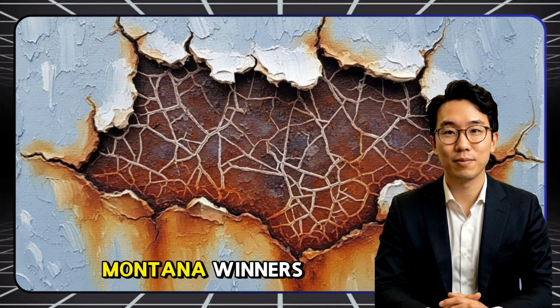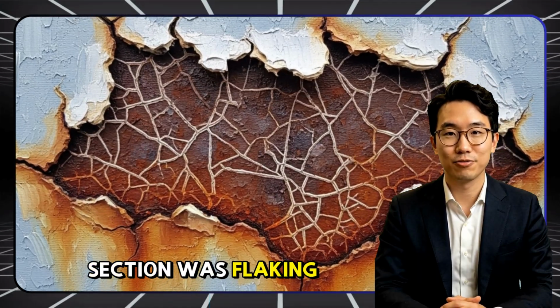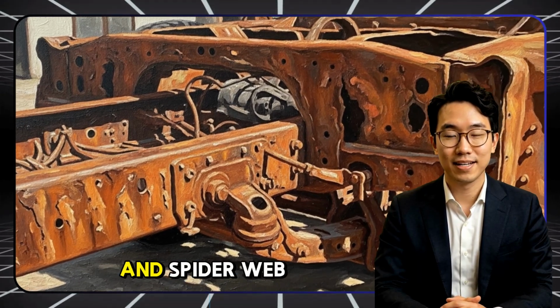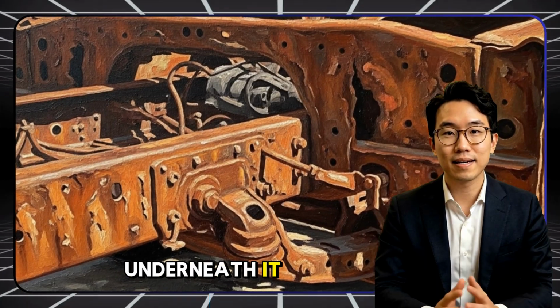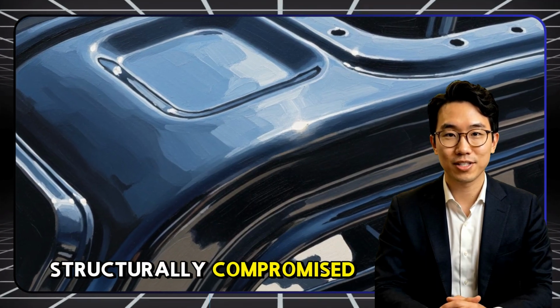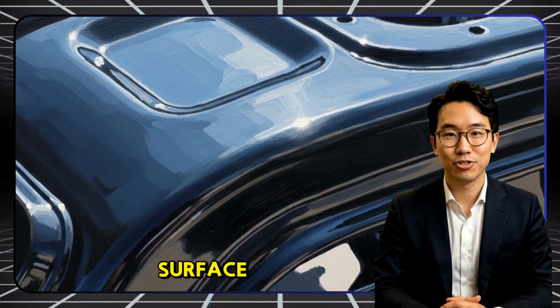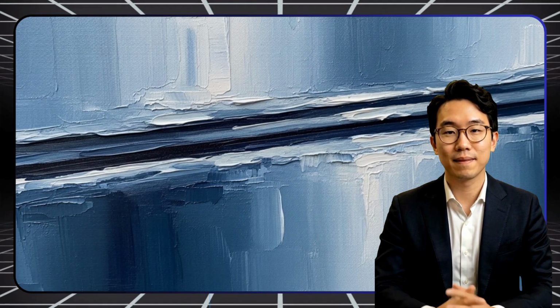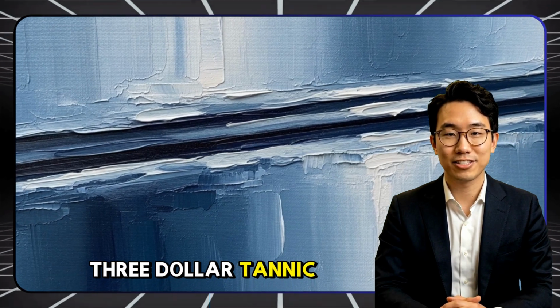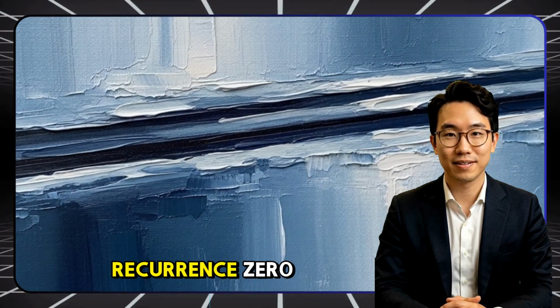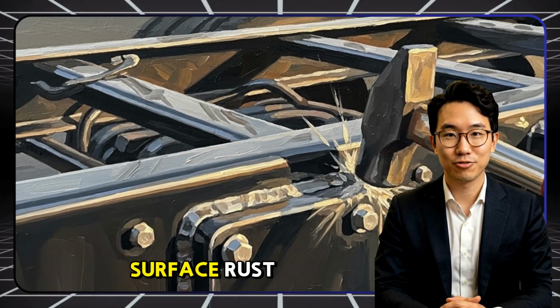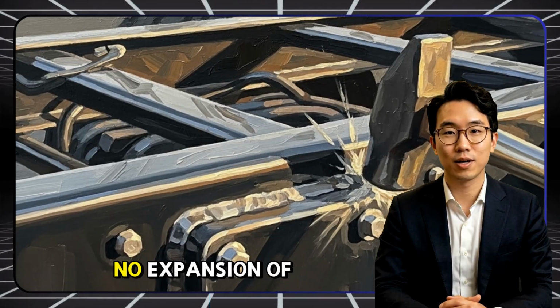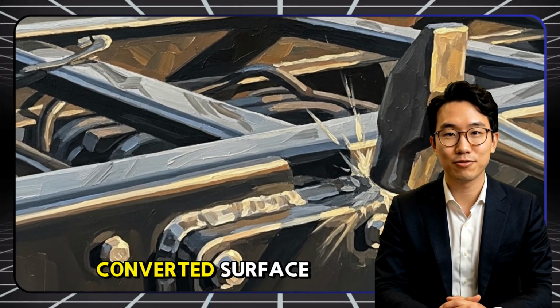After 3 consecutive Montana winters, the name brand section was flaking. The plastic-like coating had cracked and spiderweb rust was tunneling underneath it. The untreated control section was structurally compromised, the rust having moved from the surface into the core of the metal itself. But the section treated with the $3 tannic solution showed 0 rust recurrence. 0. No new orange surface rust. No new pitting. No expansion of any kind from the original converted surface.